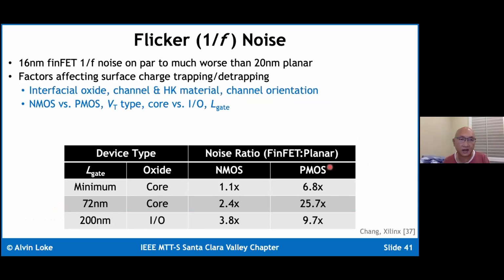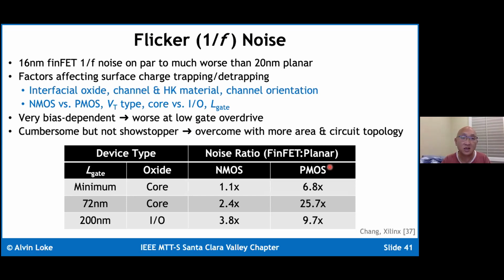Flicker noise, I mentioned earlier, going from 20 nanometer planar to 16. The claim by the foundries is 1/f noise is on par, but in reality, what we have seen is it's a lot worse. There are lots of different factors affecting surface charge trapping and detrapping, and it gets worse at much lower gate overdrives, but it's not a showstopper.